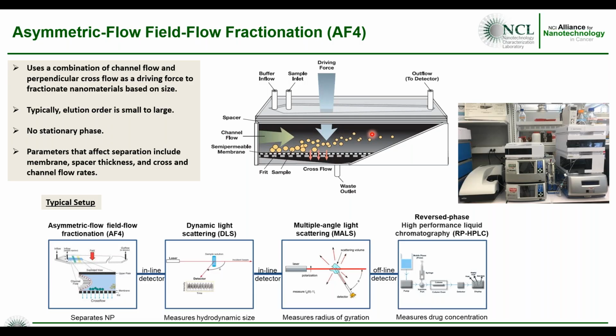Basically, it's a channel with a semi-permeable membrane on the bottom, typically a 10K, and you have a channel flow, and your sample comes through, and you basically affect a cross flow, which is your driving force, which will pin down the larger particles to this membrane and allow the smaller particles to elute first. So your elution order is small to large. There is no stationary phase in this case, as opposed to, let's say, size exclusion chromatography where you have basically a column where your particle can interact. In this case, you have just a membrane. We can change the channel flow, the spacer, the type of membrane, and the cross flow to affect separation.